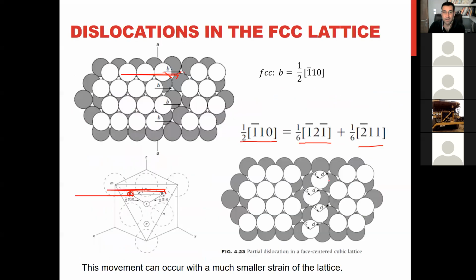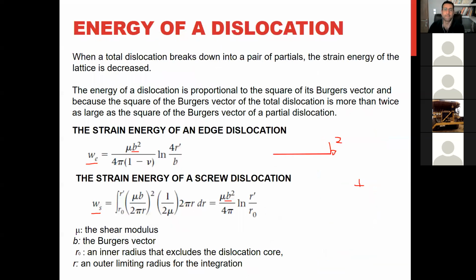So when we have this decomposition, you have to calculate this b² for this, and this b₁², b₂², yeah. If the sum of these two is less, then this decomposition can happen easily. Also, it can be a question for you. We have lots of partial dislocations, and you can evaluate whether this dislocation can decompose into these two partial dislocations or not. Okay?